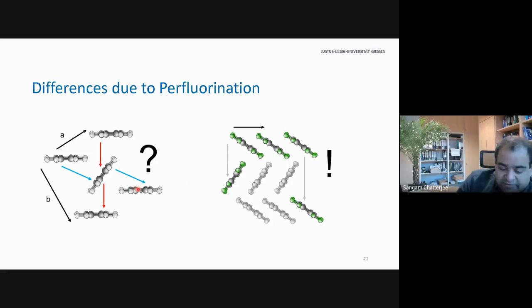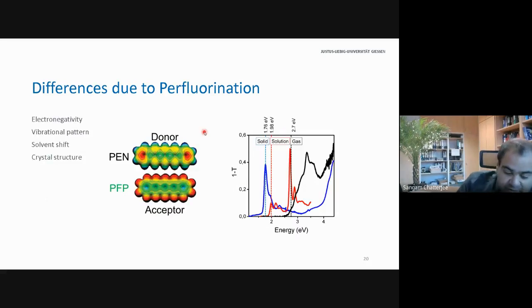So we found somebody to rip away all the H's on the outside and add all the fluorine to that. And that changes the system dramatically. For instance, you basically get a more simple crystal structure where, when you calculate the binding, the coupling between the two molecules, you expect a strong coupling along this direction where you get something like pi-pi stacking or slip stacking. Whereas the hydrogen, or in this case fluorine, to carbon coupling in this herringbone pattern should be much weaker. And that's not the only thing.